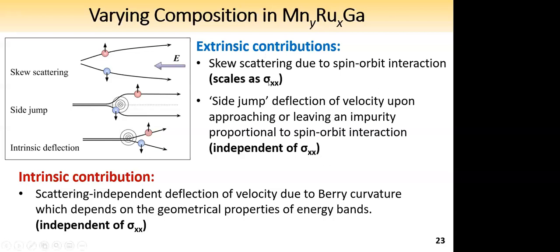So both those extrinsic contributions are expected to increase as ruthenium is increased in manganese, ruthenium, gallium, because ruthenium is the heaviest element, so it should have strong spin-orbit coupling. Then we also have this intrinsic contribution, which is a scattering independent deflection of velocity due to Berry curvature, which depends on the geometrical properties of the energy bands, and it is independent of sigma xx.